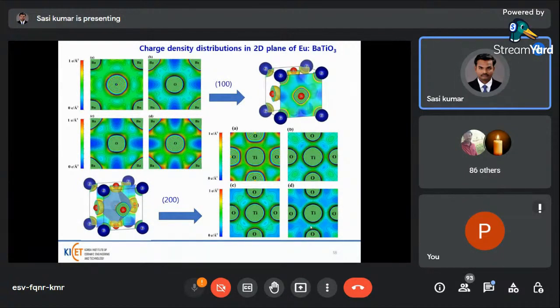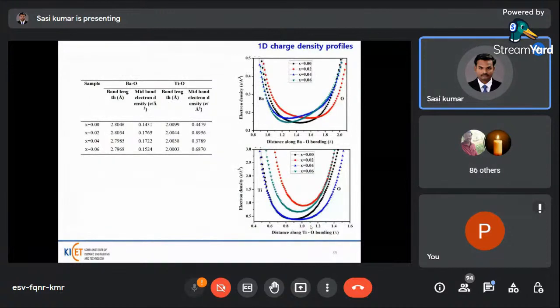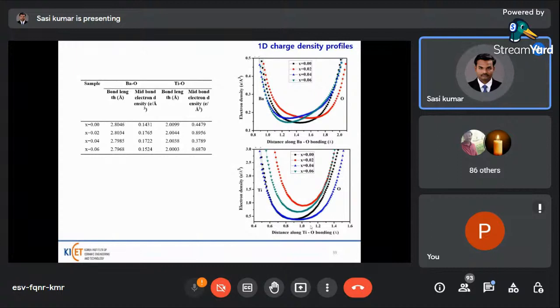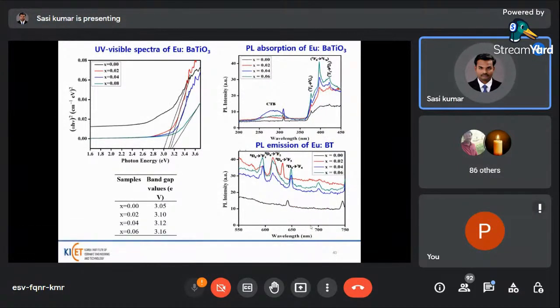And then again, the charge density distributions are plotted, two-dimensional charge density distribution on 100 plane and 200 plane also mentioned here. And then one-dimensional charge density, similarly to the previous work, also gives the bond length between Ba and O and between Ti and O, and also gives the midpoint electron density values of these two bondings. And then UV spectra of europium doped gives band gap values around 3 electron volt, and then PL absorption and emission spectra of these different compositions are well correlated with the previous ones.